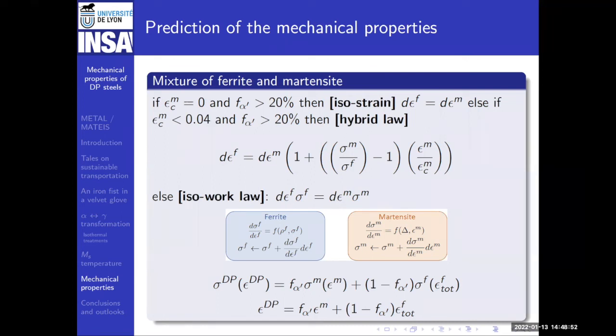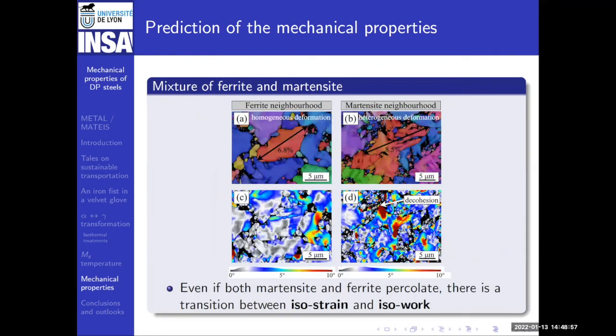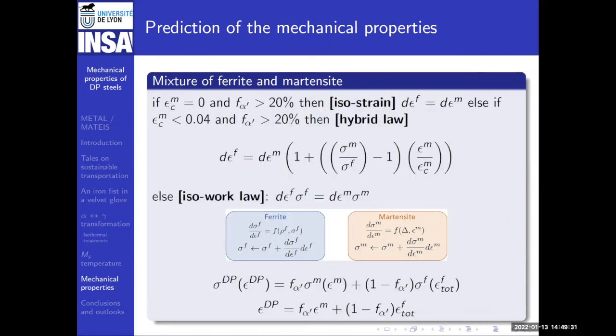How do you pick the threshold between the two models? In fact, the threshold is taken from microstructural observation. So this 4% is that we look in the EBSD maps, and we say that always for deformations that are under 4%, martensite and ferrite deform uniformly. So there is a uniform map. And above this threshold, there is non-uniformity. And it's this EBSD that told us that we have to introduce this 4%.